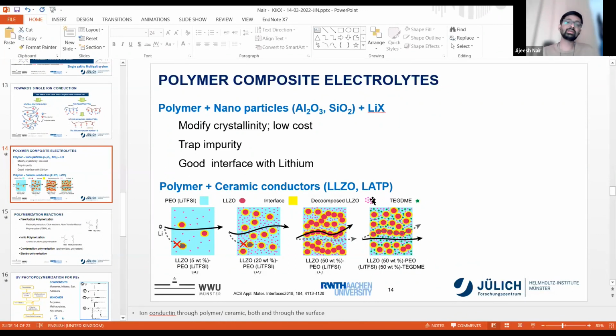At the same time, when you increase the size, for example, if you have a ceramic material with a particle size of 50 micrometers or 80 micrometers, then it becomes difficult for the processing of the electrolyte, and diffusion becomes the limit. So uniformity matters. In that case, you need more homogeneous powders with a smaller size, but you should guarantee that the interfaces are better tuned, so that you can have better lithium mobility through the ceramics if your target is a ceramic electrolyte.